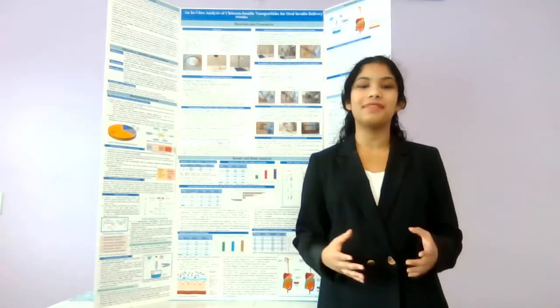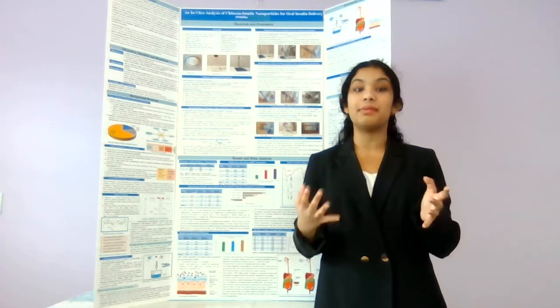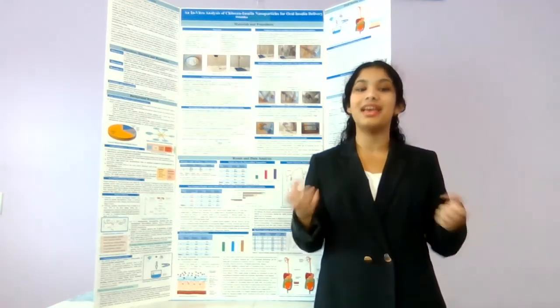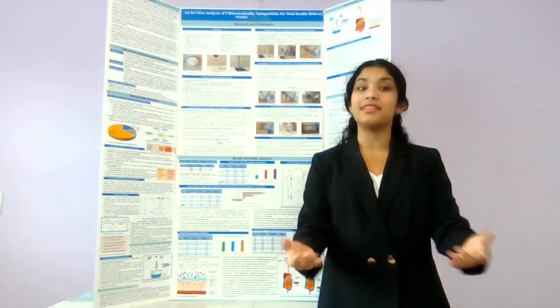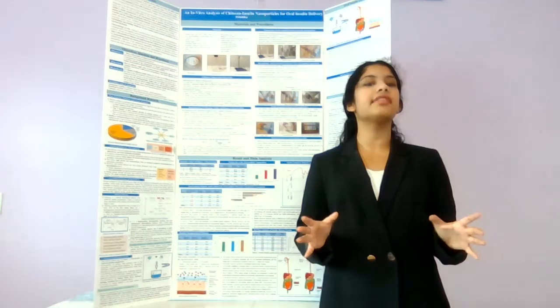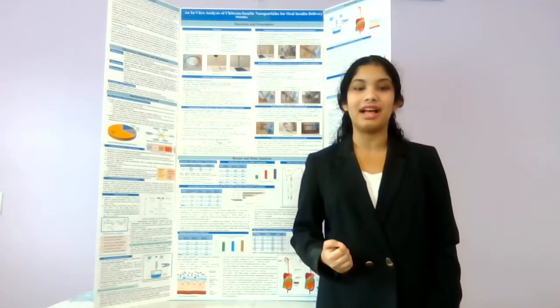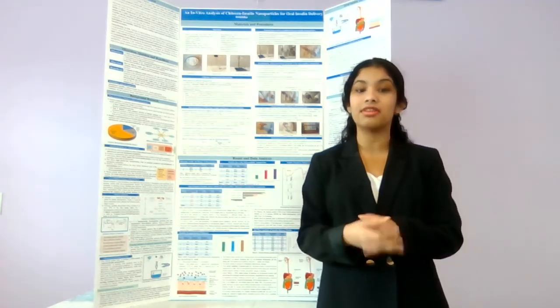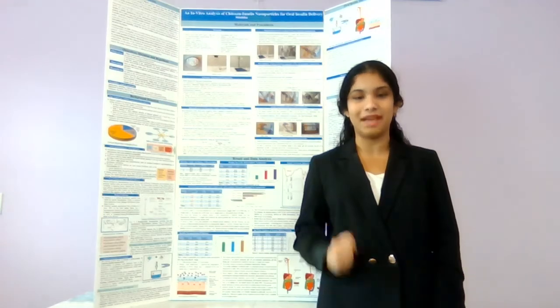And my in vitro analysis was successful as the 1:1 weight ratio demonstrated the best insulin retention and release at the right times. This non-invasive method is more efficient, cost-effective, less complex, and has the potential to improve the lives of millions. With my in vitro analysis of chitosan-insulin nanoparticles for oral insulin delivery, we can pursue a non-invasive treatment of diabetes.